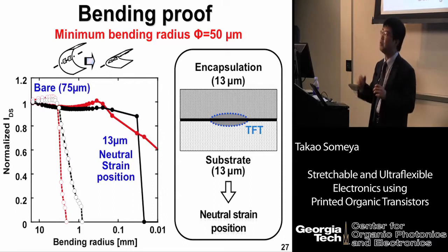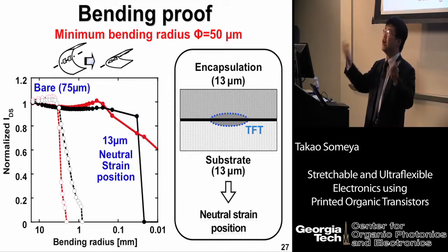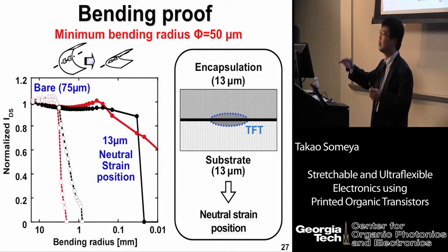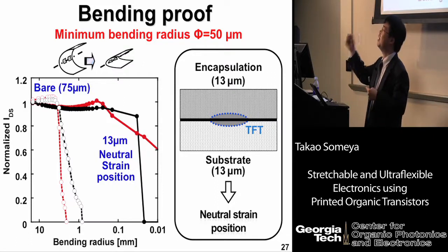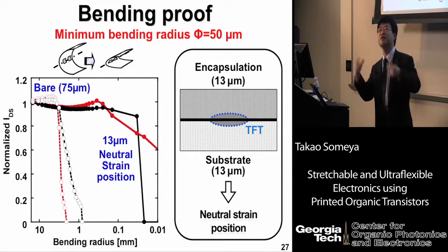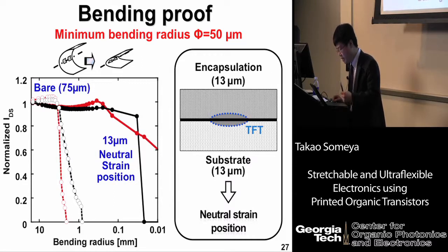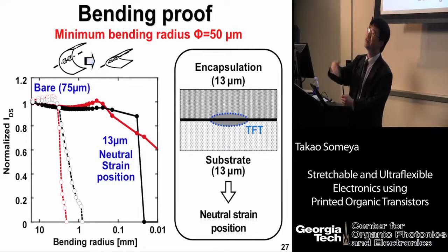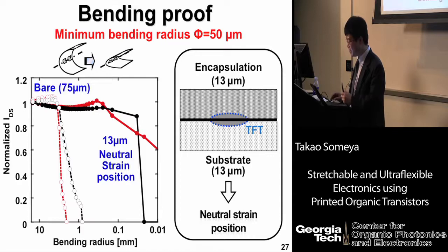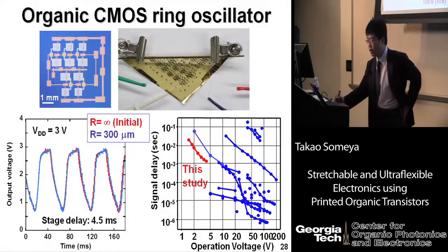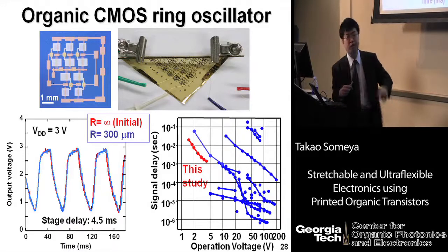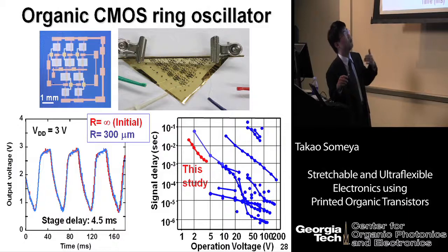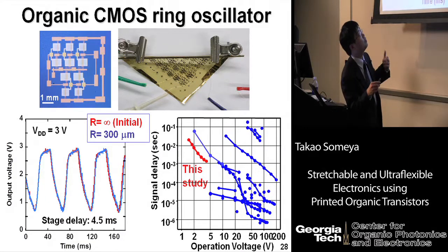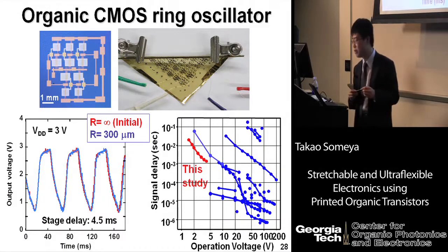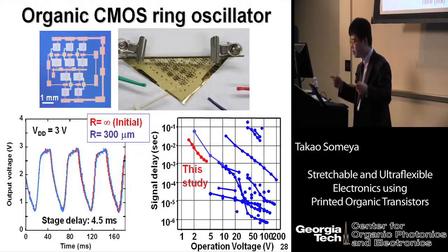Quite recently, one of my students has successfully formed high mobility transistors on 1 micron thick plastic film, and he can nicely wrap them around even a human hair, which has a 100 micron diameter, without causing any significant electronic degradation. So in that way, we could ultimately improve the mechanical durability. And also at the circuit level, here we measured the electronic performance of organic ring oscillators wrapped around a 300 micron central bar without causing any degradation in electronic performance.